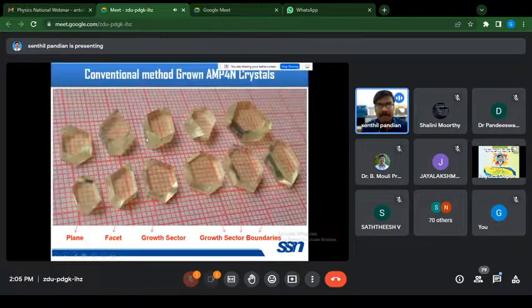Because of this kind of grain and grain boundaries, the dislocation density of these conventional method grown crystals are very high. This we have identified using EPD, etch pit density analysis. And we cannot grow the highly uniformity in the conventional method grown crystal. And due to temperature fluctuation, the several solvent inclusions are also trapped in the conventional method grown crystal that we have identified using HRXRD measurement. Not only this kind of sulfamic acid and the TGS crystal, almost all the conventional method grown crystals are having this kind of issues like multinucleation, microcracks, milky opaques, high dislocation density, less uniformity, low angle grain boundaries, and the solvent inclusion kind of thing.